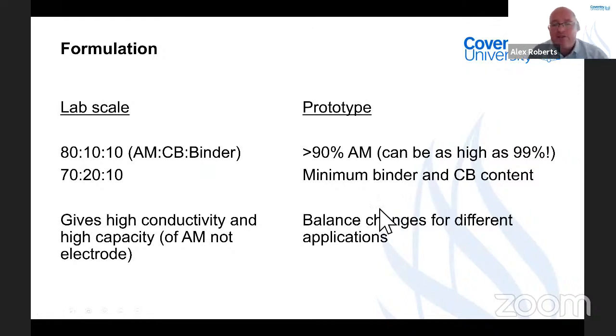And your balance changes in your formulation and prototype depending on your application, your active material. So to give an example, there are some types of LFP, lithium iron phosphate, where you may want a higher amount of binder going in there than maybe you do with an NMC or an NCA due to the properties of the material.